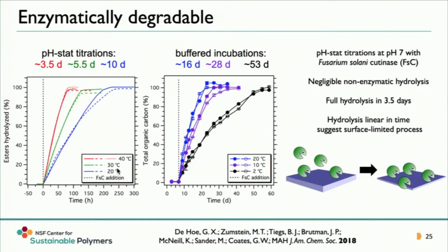And even at room temperature, at 20 degrees Celsius, over several days, you start to get full degradation of the material. And even at 2 degrees, doing a different type of experiment, even over a few months, you get full degradation of the material back down to its monomer constituents. And this picture is meant to show you exactly what it looks like. The enzymes actually coat the surface and end up hydrolyzing those ester bonds in the backbone.